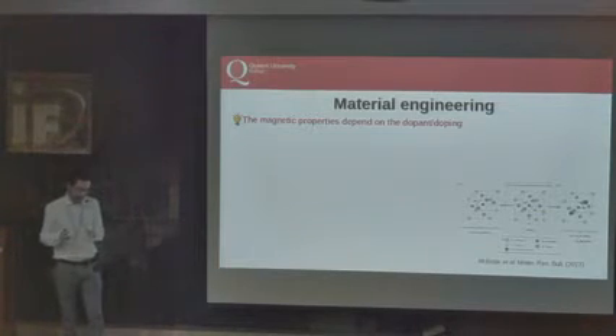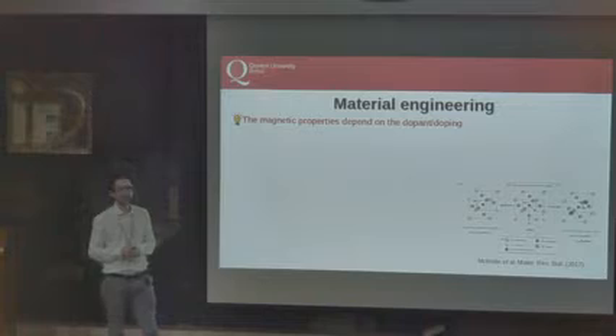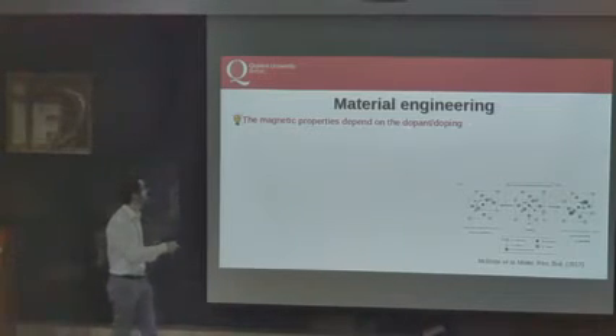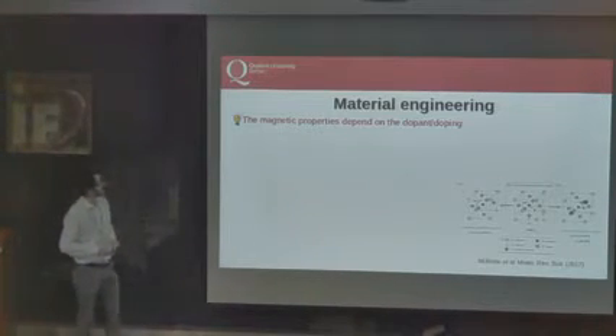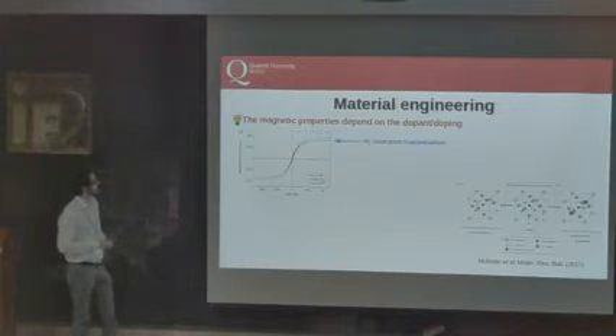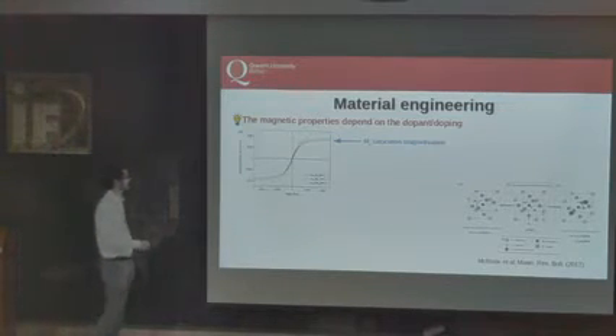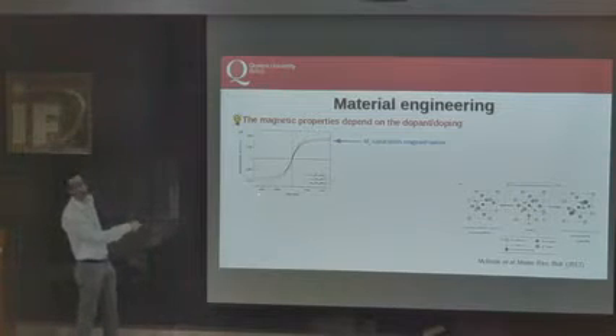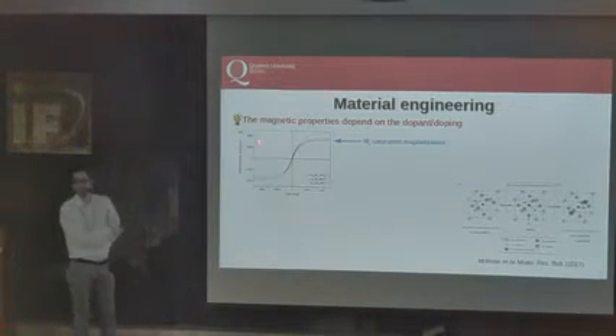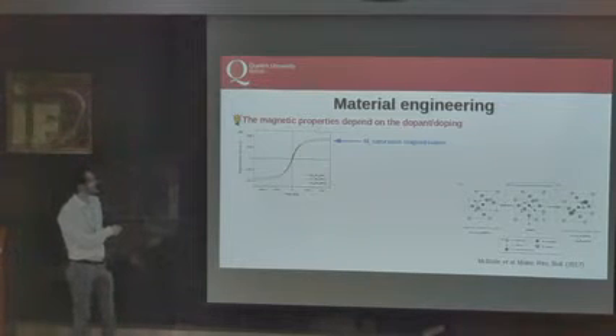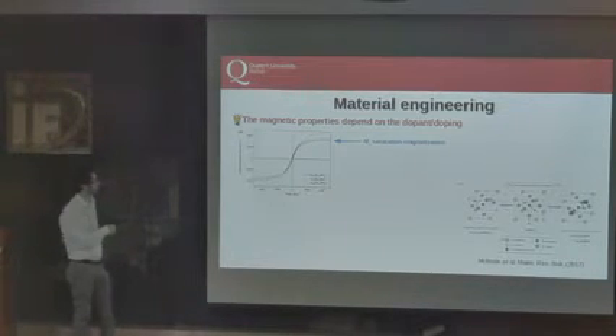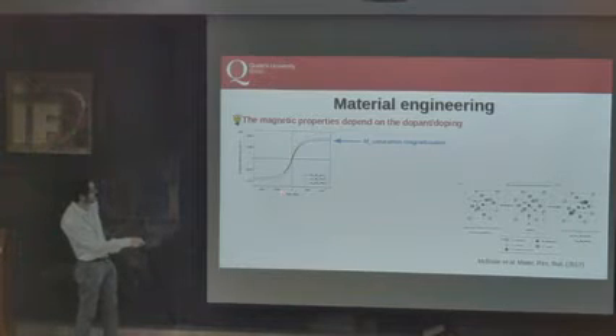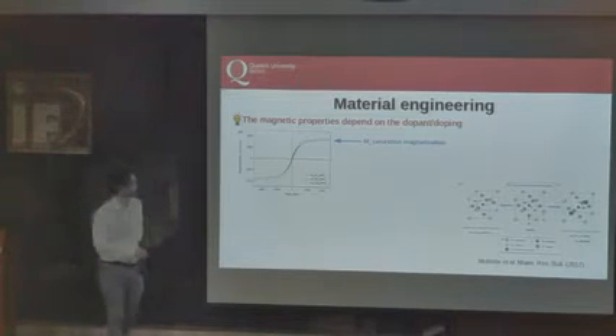As I said before, those are complex materials. The properties depend on the dopant, the doping, and the synthesis. Let's start with the dopant and the doping. This is the magnetization. Again, we use EMU units, CGS units. Magnetization as a function of the applied field, and those are 4,000 Oersted, so those are 0.4 Tesla, I think.